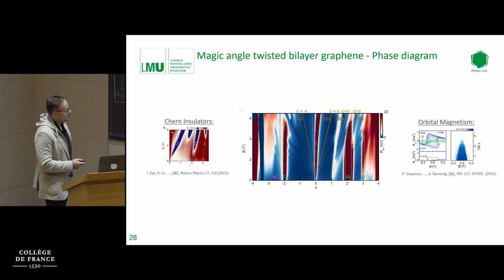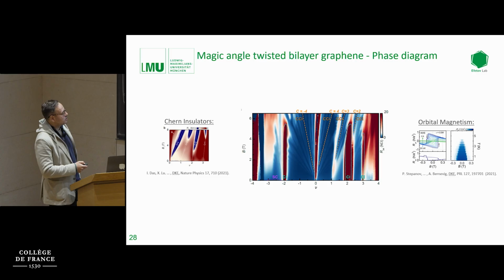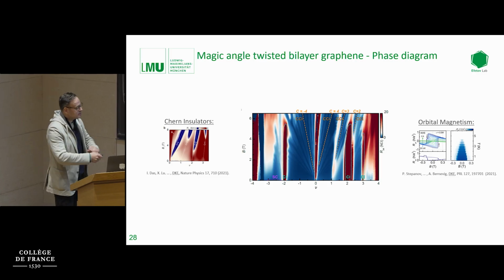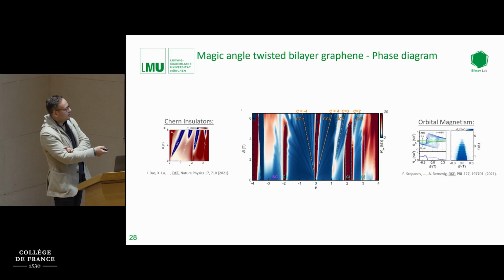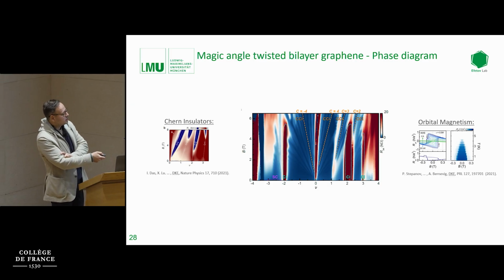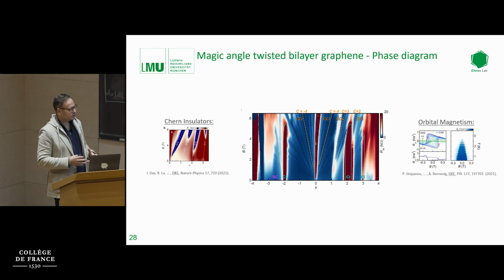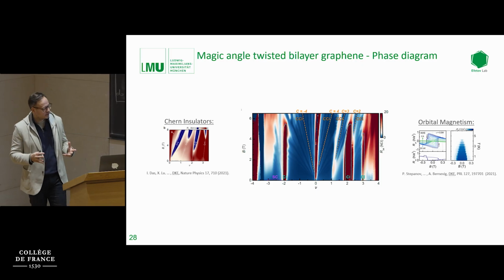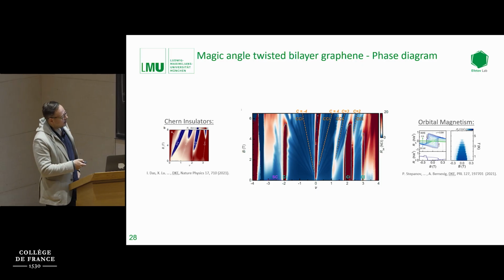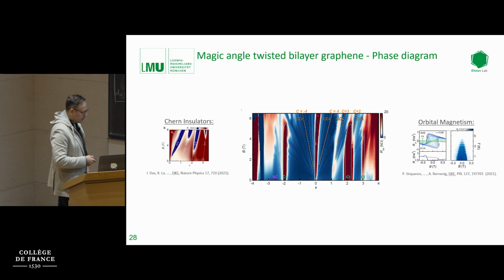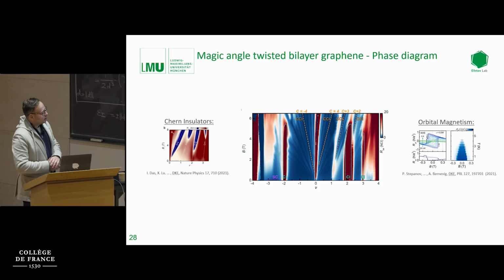And just to give you an idea, for this matter, what's more useful is the phase diagram as a function of magnetic field. So this is basically a typical high-quality phase diagram in magnetic field, where we still measure Rxx, but now as a function of magnetic field on the x-axis. What you see here is a very rich sequence of quantum Hall phases appearing, which are identified by these Landau fan lines. Each of those lines is somehow a Landau level that you can characterize.